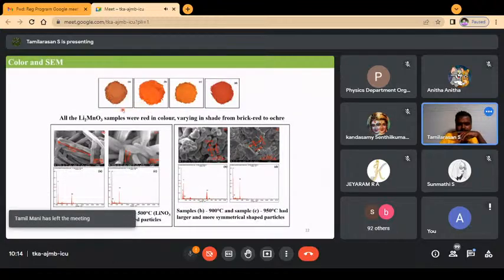But we wanted to follow up about its color and what is the reason for its unusual color, because manganese 4 plus is supposed to be dark brown or black in color. So we synthesized 4 different samples using 4 different methods: solid state, flux, sol gel, and combustion, with different temperatures. And we got the same compound Li2MnO3 with no doping, nothing, but different shades of red, with this one being mostly orange, and this one being more like hematite red in color. And we characterized it and then found this material having orange color is really nano in size.